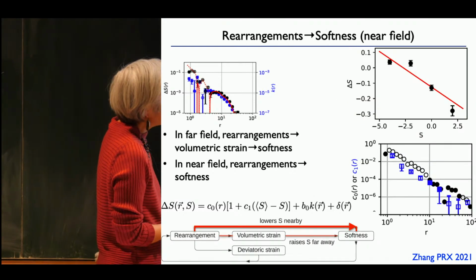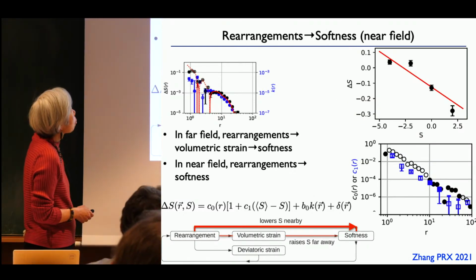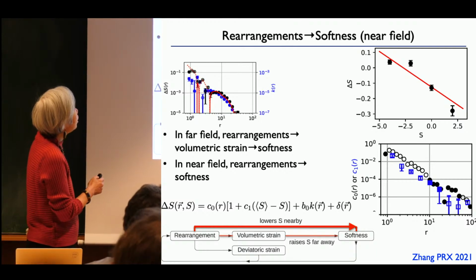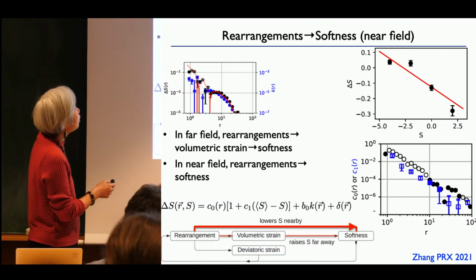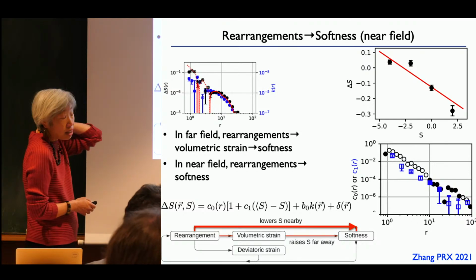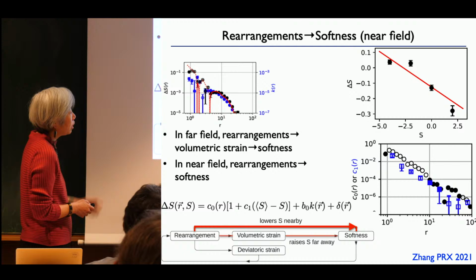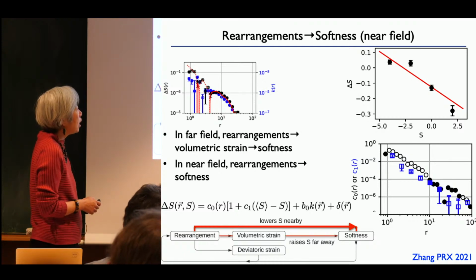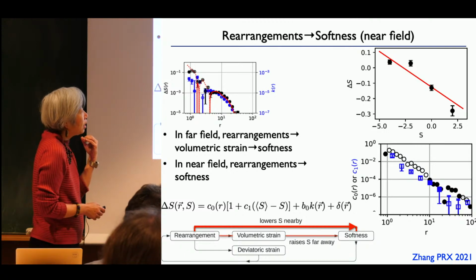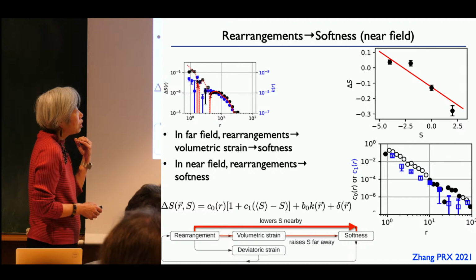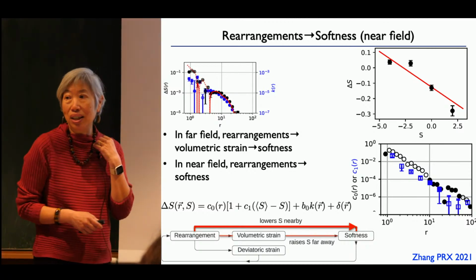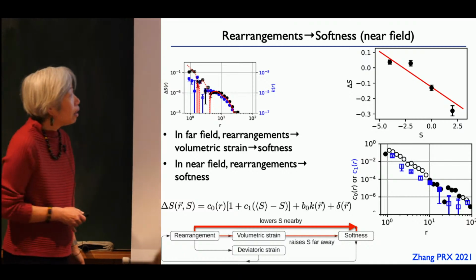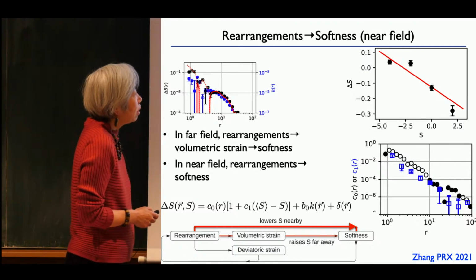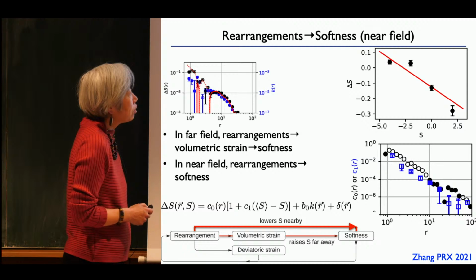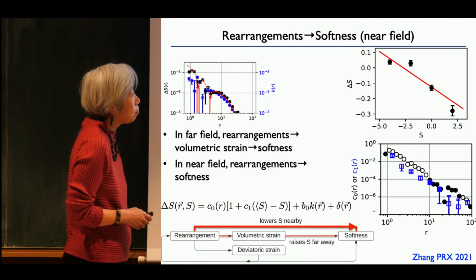All right. The near field term is more complicated. What you see is that in the near field, the change of softness does not agree with the volumetric strain at all. But if you subtract off the volumetric strain piece, it turns out that it's quite simple. There's a piece that decays with distance from the rearrangement, and then there's this piece which wants to restore softness to the average of the neighbors. So this is the effect nearby.